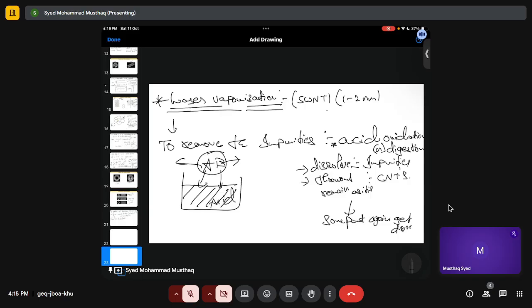And when we decrease the concentration, the dissolution will depend upon the concentration. If you have a high concentration of acid, the dissolution will be very fast. If you have a low concentration of acid, the dissolution will be very slow, right? So if you have very high dissolution, everything will get dissolved. That is not required, right? We need low concentration, but only the impurities should get dissolved, and that will take time because we are playing with the concentration, right? So again, that's why they are very time-consuming and very expensive. But still, they are being prepared. Why?